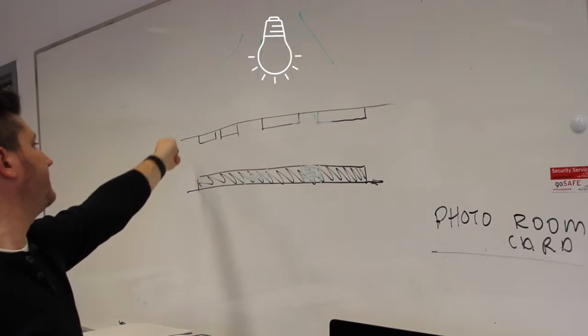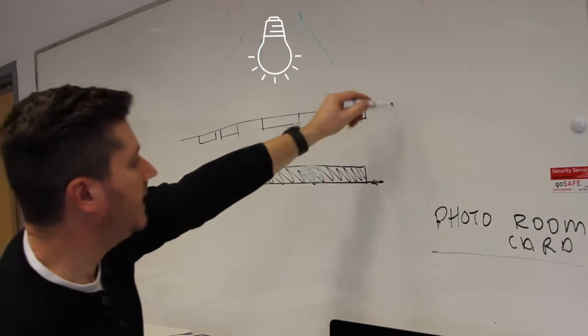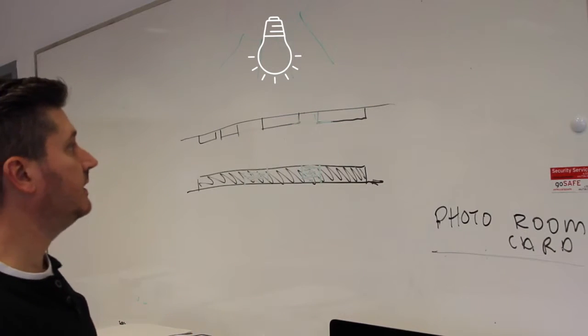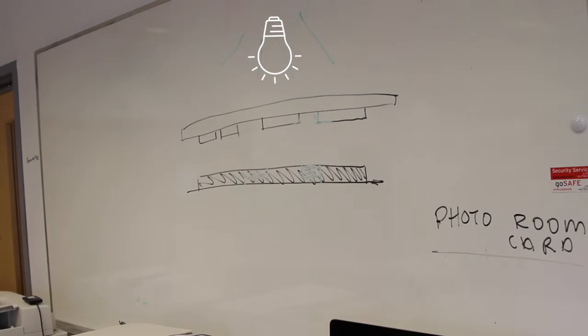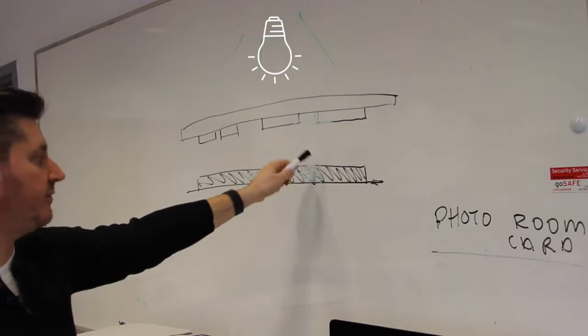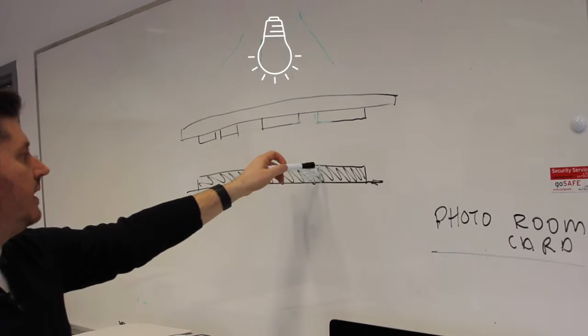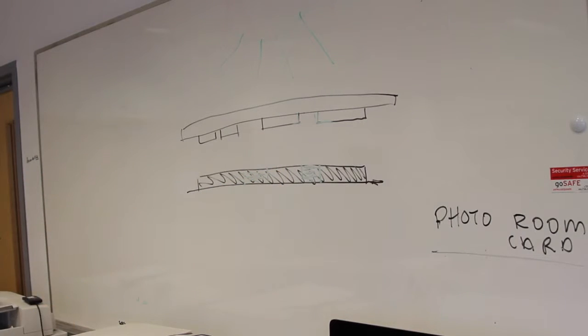If this ortho film were turned upside down, the thickness of the carrier material, however small it may be, may cause the light to bend and therefore giving you very soft edges on your final result in the polymer and therefore not giving you a good quality polymer plate.